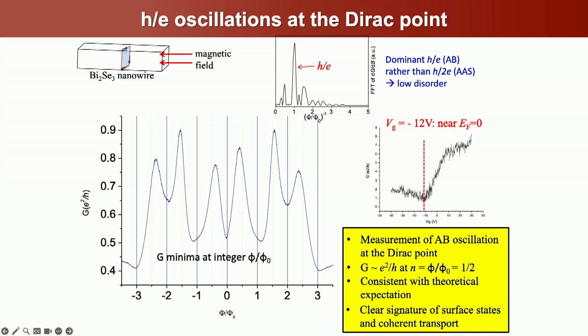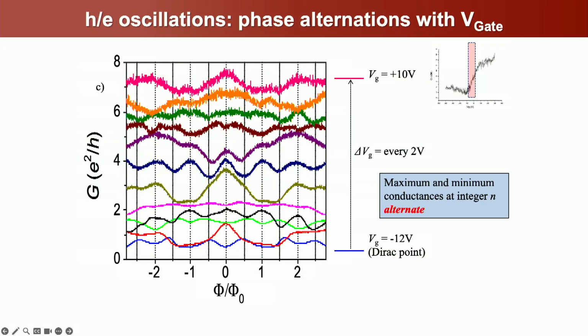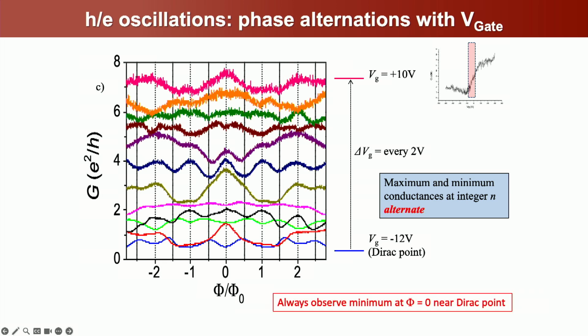We also see, if we measure this as a function of gate voltage, without going through the details, if you look at zero, you can see the alternation of the phase. It goes from a dip to a peak, to a dip, to a peak, to a dip, to a peak. And this maximum and minimum alternation is due to passing through 1D subbands. Now, I'm not saying that we hit every 1D subband with our gate voltage, because I think we probably get a couple at a time, but the fact that we see this phase alternation tells us that we are indeed in a regime where we can access 1D subbands, which is, again, interesting, as I'll show later, for different sorts of applications involving topological materials. Okay. And we also always observe a minimum near the Dirac point, which is what's expected theoretically from the topological regime.